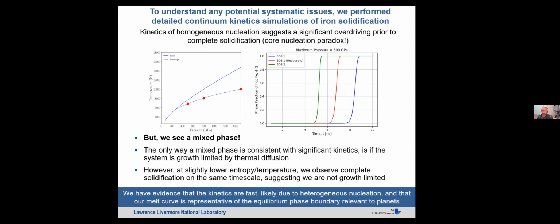One of the first things they looked into was assuming homogeneous nucleation with reasonably calculated thermal diffusivities and surface energies. They found that, assuming homogeneous nucleation, you have to overdrive this a lot. And this is consistent with the idea of the core nucleation paradox, right? The core nucleation paradox says you have to overdrive and undercool the iron really significantly in order to nucleate a core. Their simulations are consistent with that, assuming homogeneous nucleation.